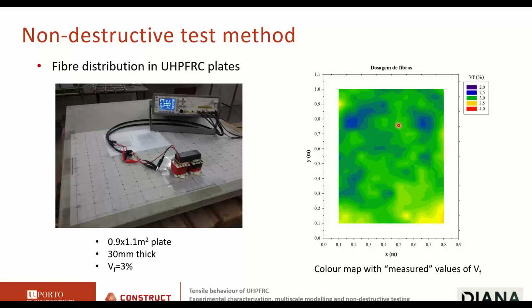So, some examples to finalize. Here we cast a plate, nearly 1 square meter, 30 millimeters thick, with a theoretical volumetric fiber fraction of 3%. And here we have the results of our measurements. Here is the contour map with the measured values of the volumetric fiber fraction. The theoretical value was 3. We can see values ranging from a little bit above 2.5 to a little bit below 3.5.